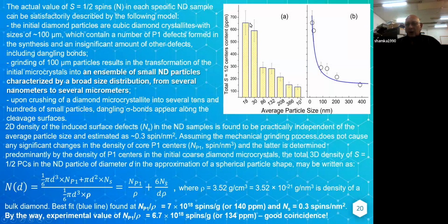Here is the result of the concentration, and very simple calculations which show that it should be so when, and it was justified experimentally, the surface density of dangling bonds doesn't depend on the size of the particle. It's logical. The initial particles are cubic diamond crystallites with sizes of about 100 micrometers, which contain a certain amount of P1 defects of substitutional nitrogen. It depends on the synthesis.